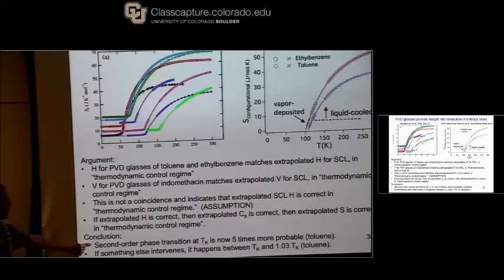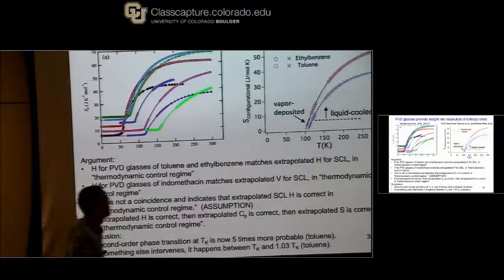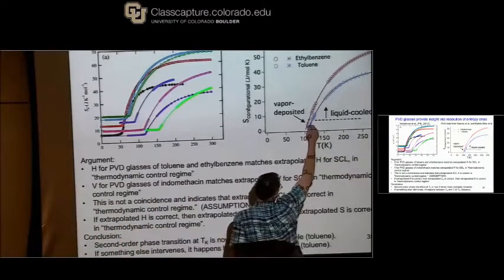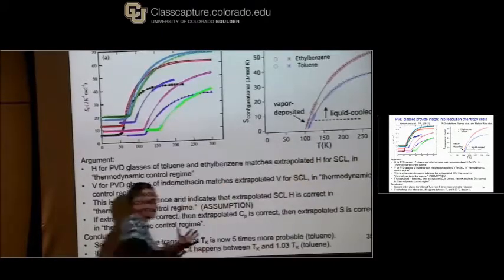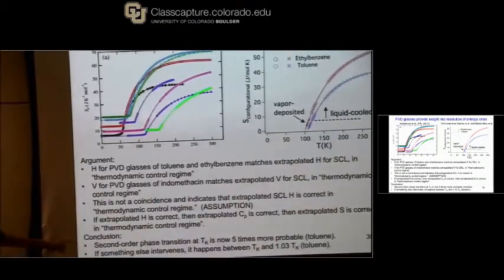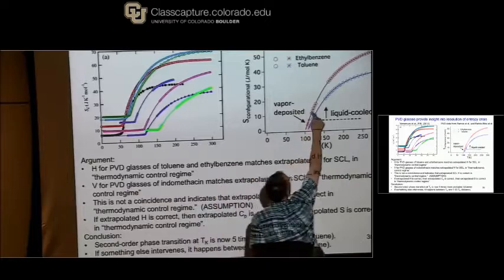From my view, a second-order phase transition at TK, which is what I would call this if it comes down to 0 and then there's a kink in the entropy, is now 5 times more probable than it was before we did these experiments, because we've closed the gap between what was measured before and what's measured now by a factor of 5. At least for toluene, it's a factor of 5. For ethylbenzene, it's 3 or 4.